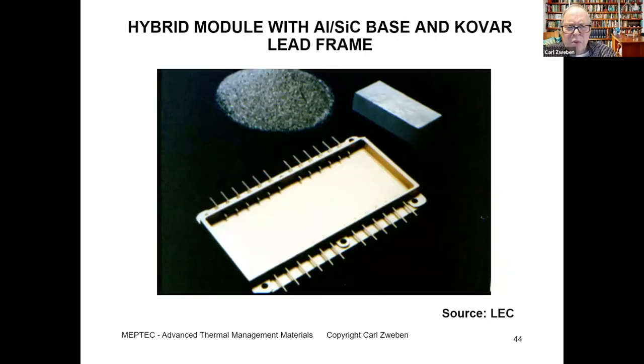So here we have some work from a company called LEC. At the top, we see silicon carbide particles in a block of aluminum. And this is what we're calling a hybrid module, which has a Kovar lead frame with an ALSIC base. The ALSIC base matches the CTE of the Kovar and provides the thermal conductivity in the base, which is where you need it. So you can combine materials.